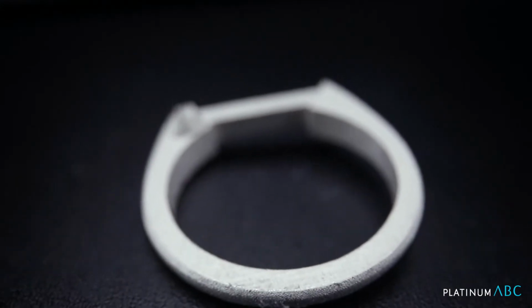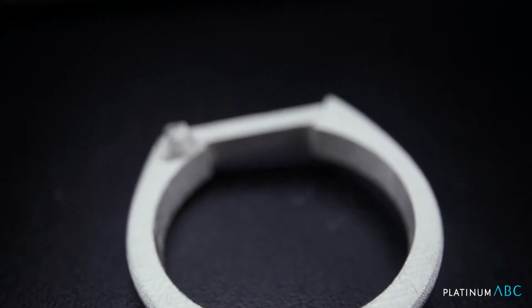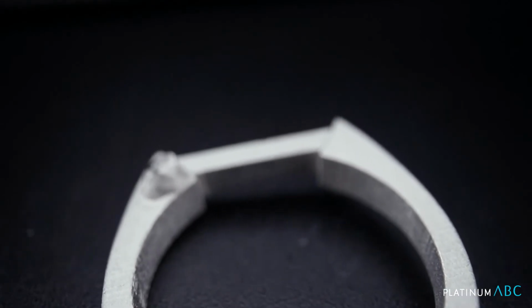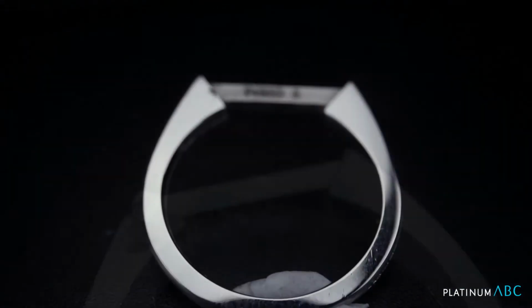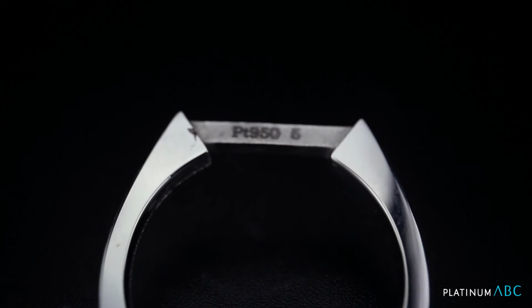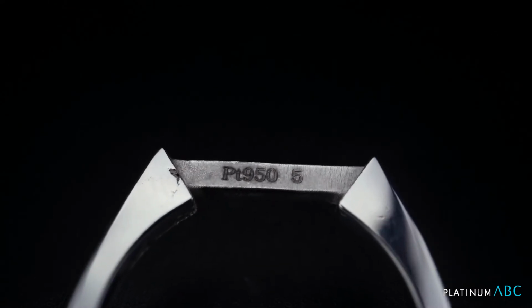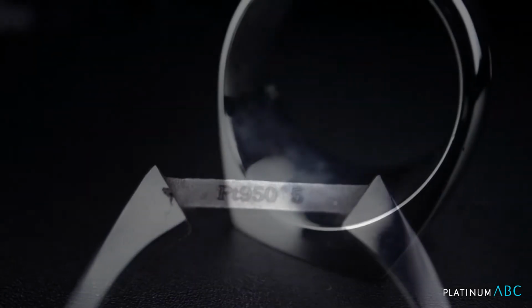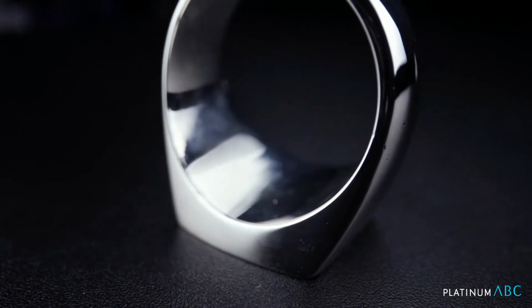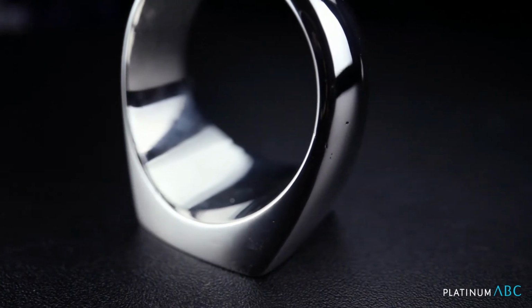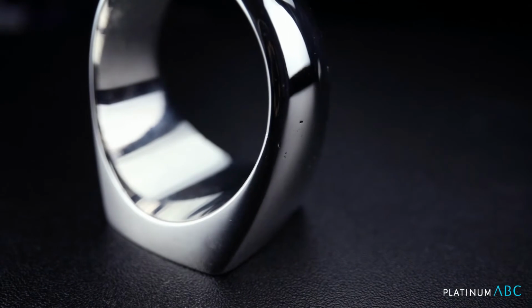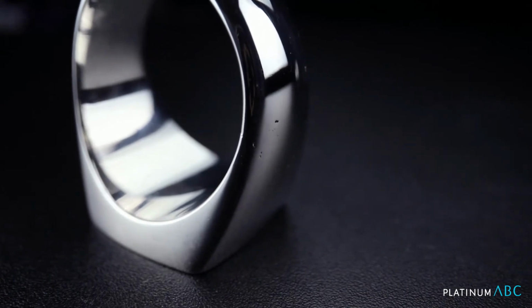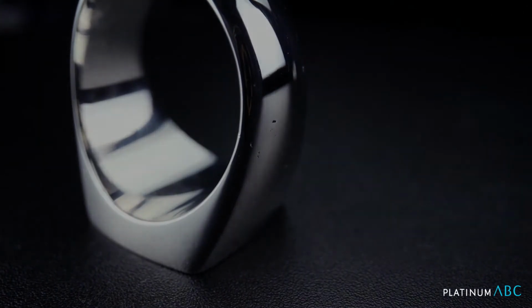The bad news is that adding the gallium does not improve porosity. Here we see platinum Ru gallium is not porosity free. Notice this ring with a heavy metal section at the top. We still see porosity at the surface as we normally would with platinum copper or platinum ruthenium. So there is no clear evidence of less porosity when gallium is added.